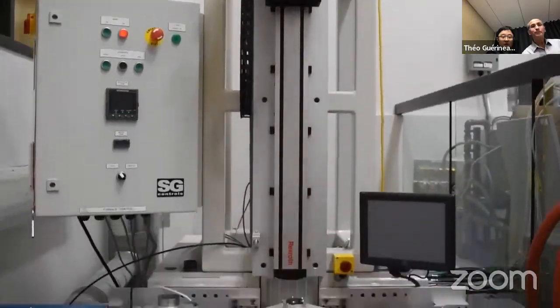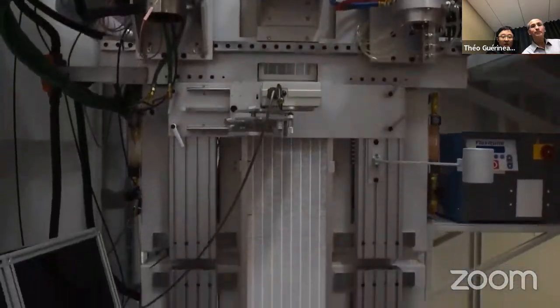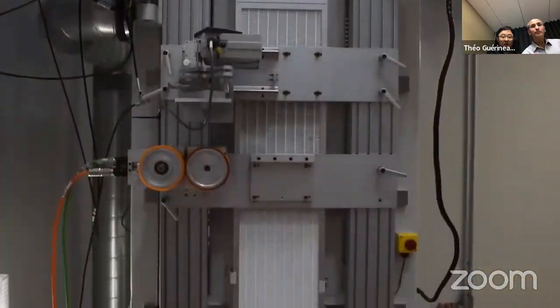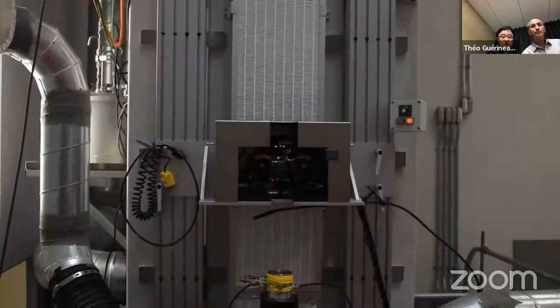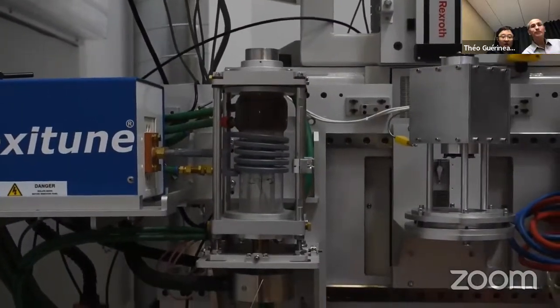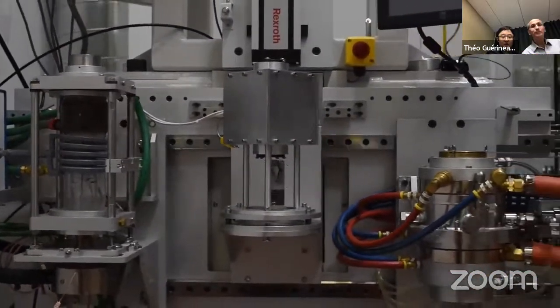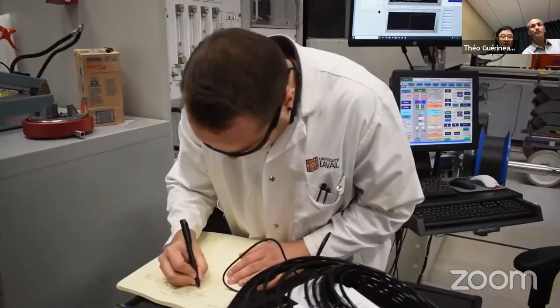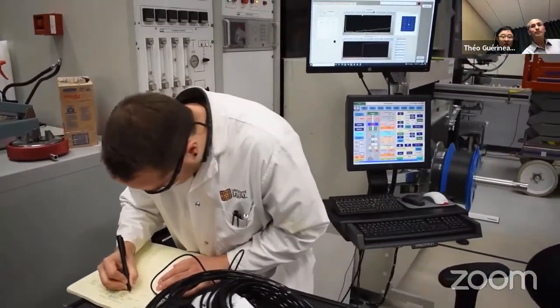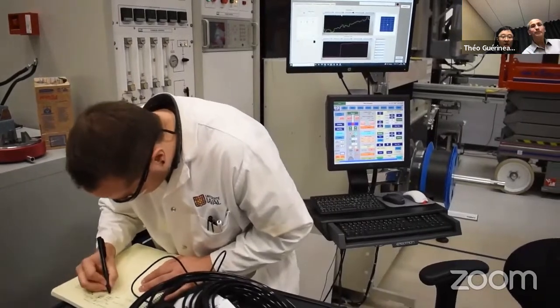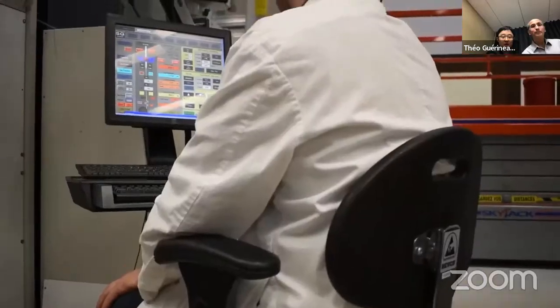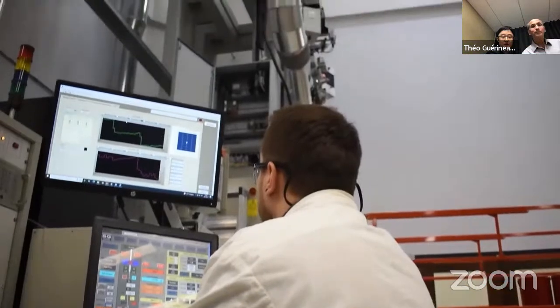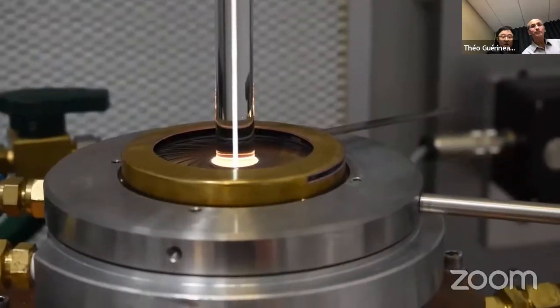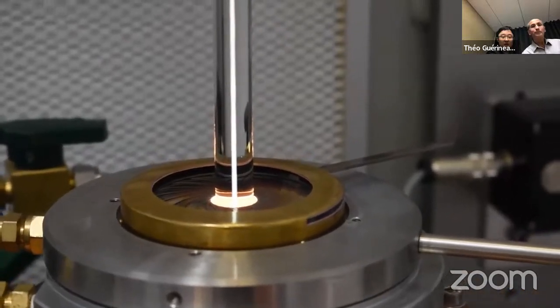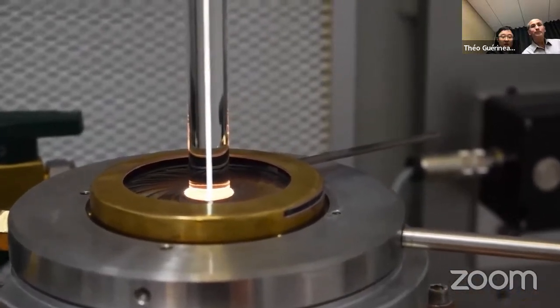On the second tower, non-silica glasses, also known as exotic glasses, can be drawn into fibers. We have a set of 4 furnaces at hand to choose the best drawing conditions. For example, a double crucible furnace is frequently used for chalcogenide fibers, where molten core and cladding glasses are inserted one into another just before drawing. For compositions prone to crystallization or chemically sensitive, a furnace with a controlled atmosphere is put in place.